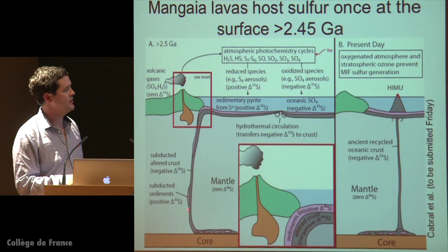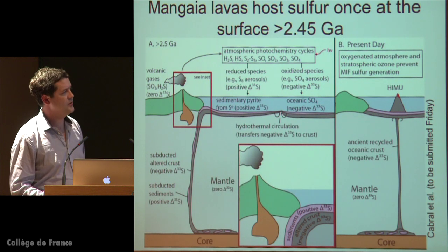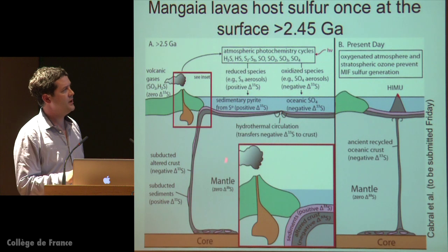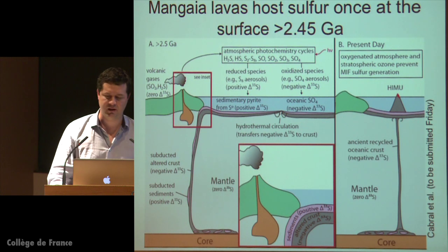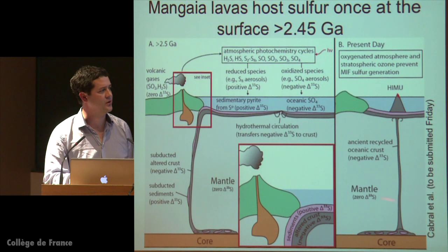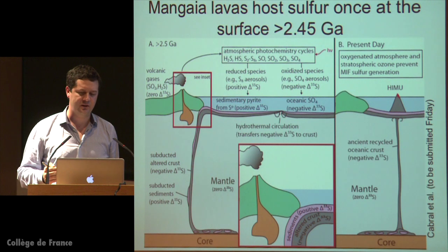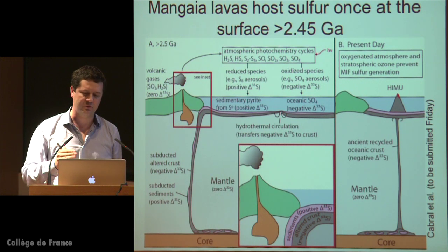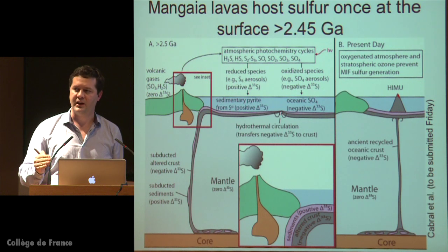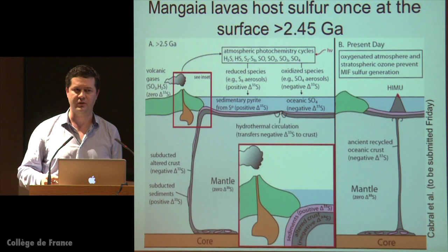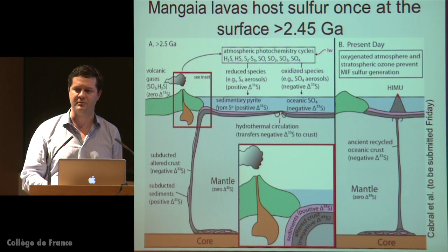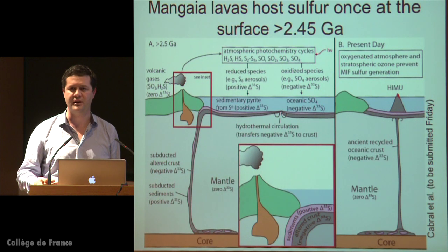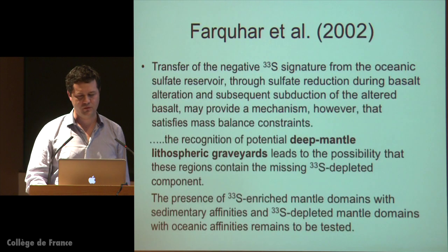If you really can send material down into the mantle in the Archaean and preserve it for 2.5 billion years or more, we find that we can then sample this material again in hotspot lavas that are relatively young, 20 million years old. So by finding these kinds of anomalies, critically you can place a timestamp on the age of different mantle reservoirs, whether they formed before or after 2.5 billion years. And it's a certificate as well that these reservoirs were at the surface before 2.5 billion years ago. So it's giving you strong evidence of recycling, and it's giving you also a timestamp. I think of this as the equivalent of beryllium-10 for hotspots.